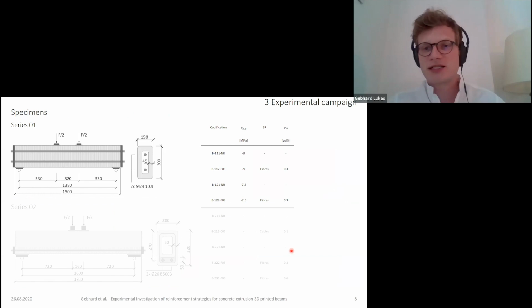Now, for the experimental campaign, we had two different series, as already mentioned. So the first series covers the post-tensioning with unbonded post-tensioning reinforcement. We produced 4 beams, always one set with transversal reinforcement. Here we used fibers at a concentration of 0.3%, placed only in the webs of the beams, and always an identical beam without this transversal reinforcement.